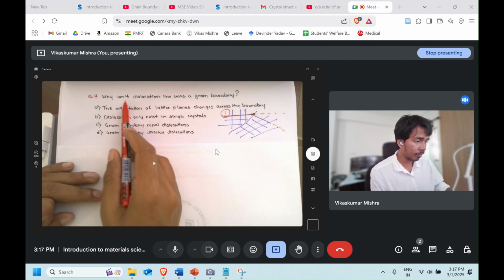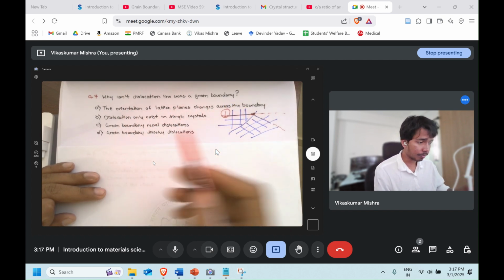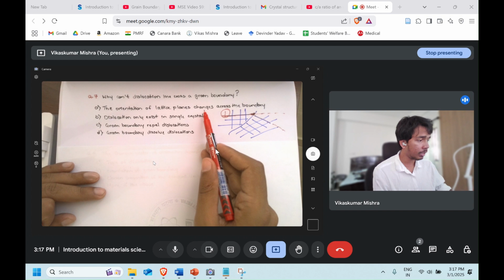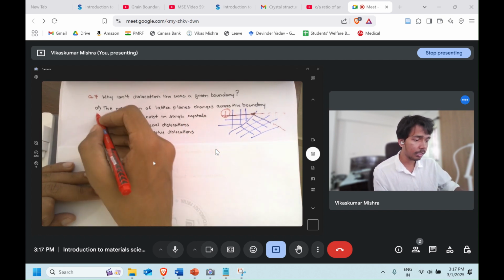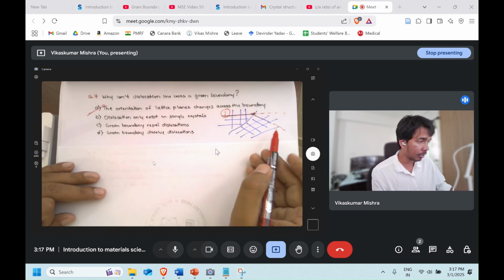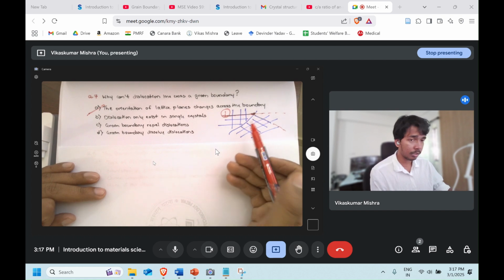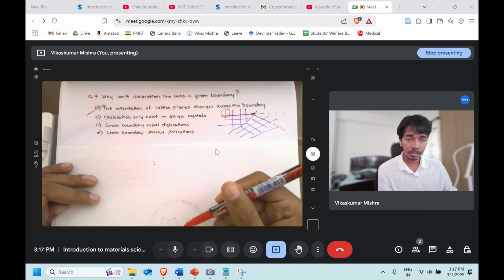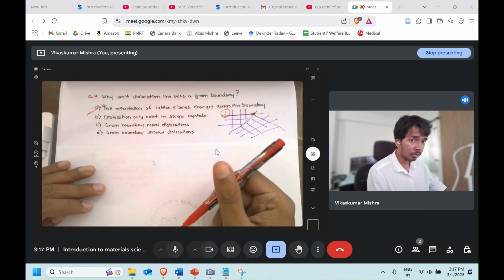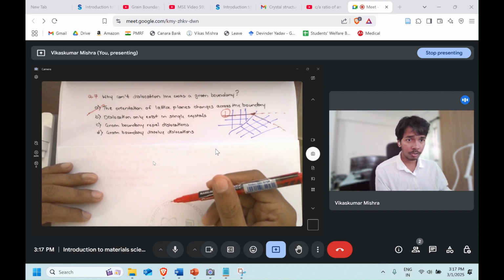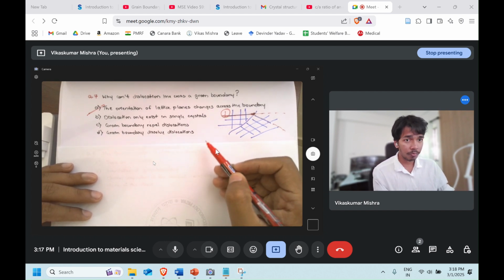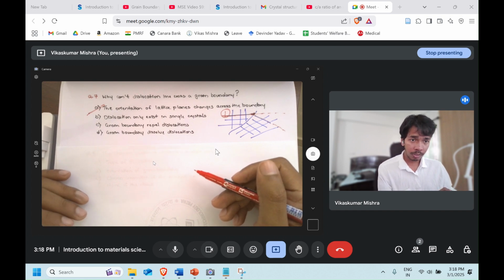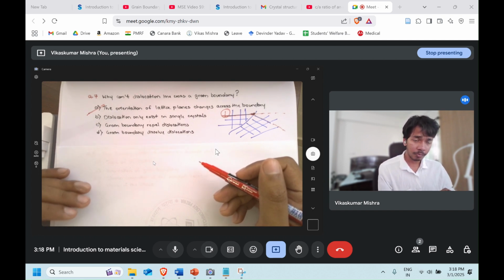So now this is the question: why can a dislocation not cross the grain boundary? The orientation of the lattice plane changes across the grain boundary. That is right, and we know that this is the case over here. If the lattice orientation changes, the slip plane will also change its orientation, and so the dislocation will not find the same oriented slip plane as it had before.